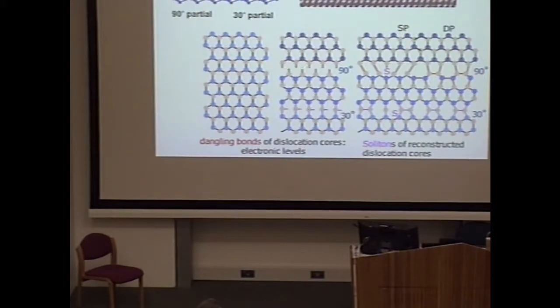But these dislocations reconstruct to save energy, and the dangling bonds make some bonds, and a certain reconstruction appears here. This is a single period, and here it is a double period, on the 90 degree partials. And these dangling bonds of the dislocation cores show electronic levels. And this is his data, this is the database.